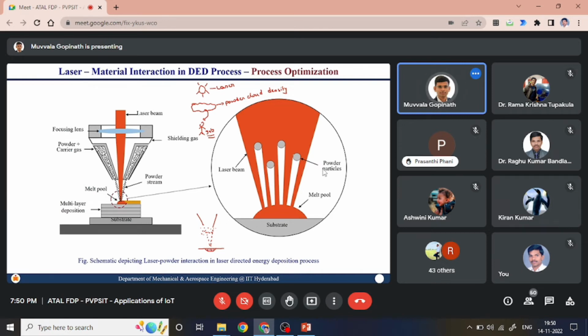The powder which has already interacted with the laser gets heated up, but it will not melt. That powder particle will come and sit over here. Now after this instance, what happens? The laser will try to fall on this powder particle sitting on the molten pool. So this particle is now taking heat from the laser as well as from the molten pool at the bottom. With this heat, it will tend to melt, making a molten pool like this. So this is how the process happens.